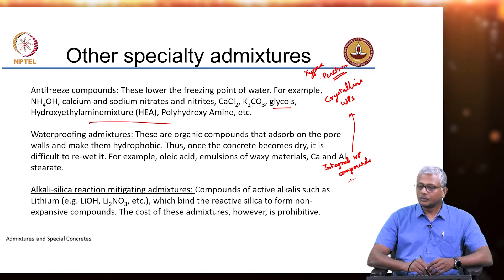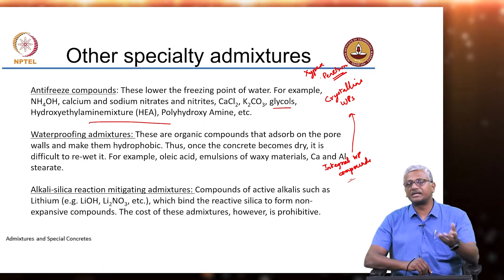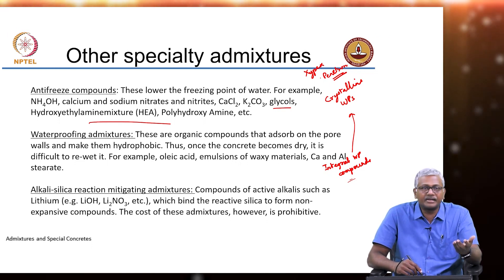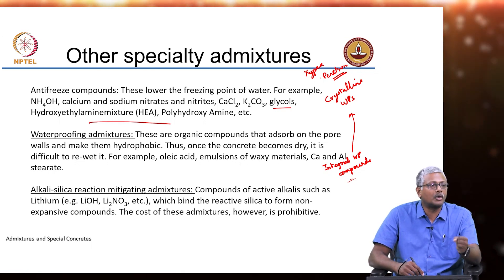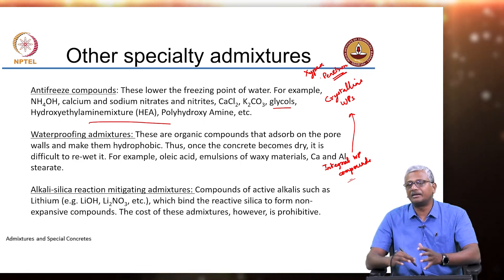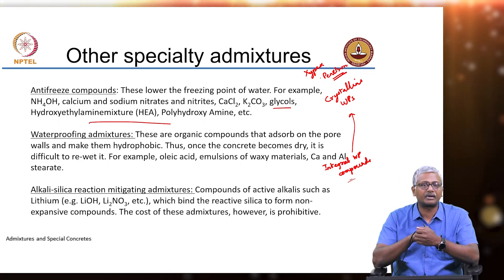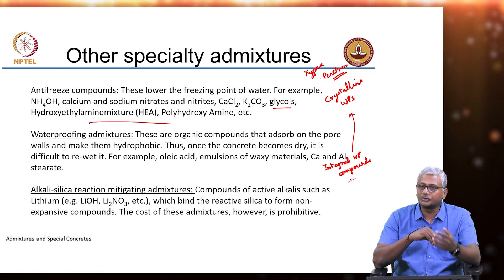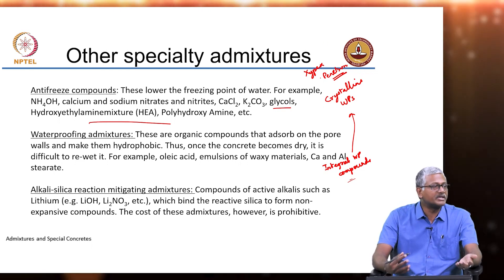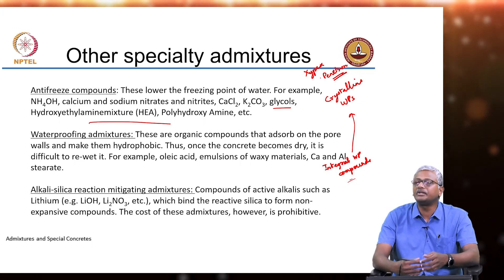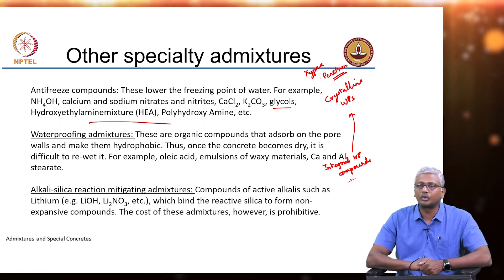If you use a lithium-based salt — lithium hydroxide or lithium nitrate — these react with the silica much before the alkalis from the cement, which are sodium or potassium. If you have lithium compounds present, they bind the silica into non-expansive products. But if sodium or potassium are there, they bind silica and form expansive gels which create pressures in your concrete and lead it to crack. So lithium-based admixtures could be used to mitigate alkali-silica reaction, but they are very expensive. A much simpler and robust strategy to protect against ASR is to simply use mineral admixtures like fly ash, slag, or silica fume — they are much more effective in controlling alkali-silica reactivity.